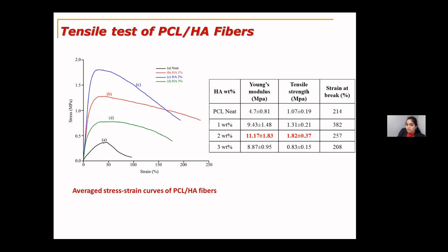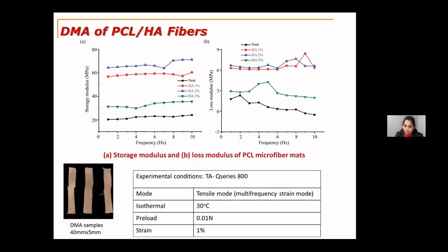This is for the tensile property or the Young's modulus, and these polymer nanofibers also have very good viscoelastic properties. So in order to check the viscoelastic properties, we did a dynamic mechanical analysis of these fibers. That was done using the TA Q series 800 equipment. For testing this particular nanofibrous mat, we chose to use the thin film clamp, which is under tensile mode, and we used it under multi-frequency strain mode. So this is the frequency sweep